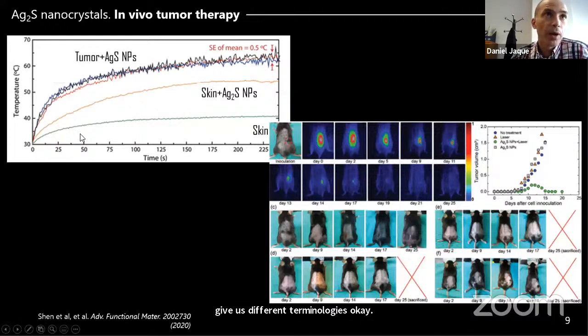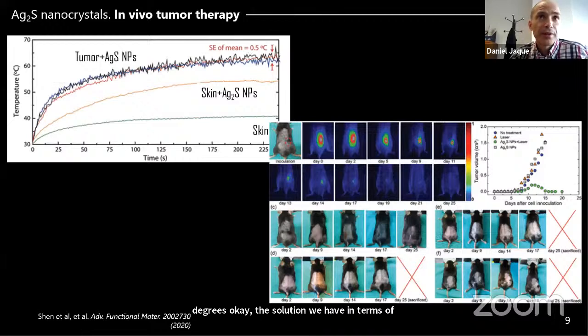And these are the results. When we have the tumor with the silver sulfide nanoparticles and we illuminate the nanoparticles, the temperature of the tumor rises a lot, and the temperature of the tumor is almost close to 60 degrees. The resolution we have in temperature determination of the tumor is 0.5 degrees.